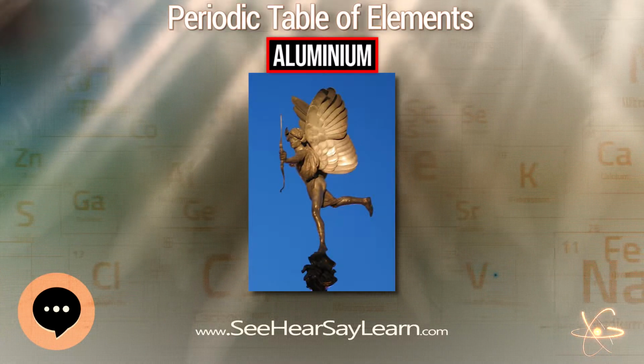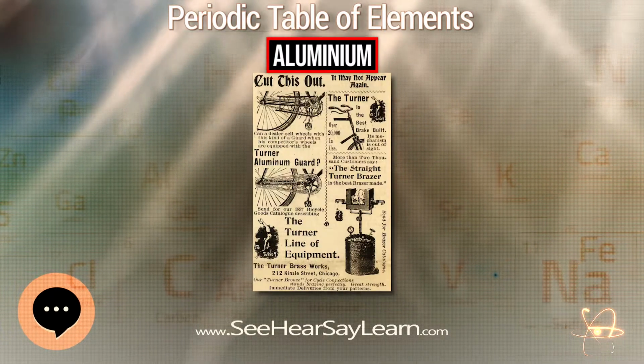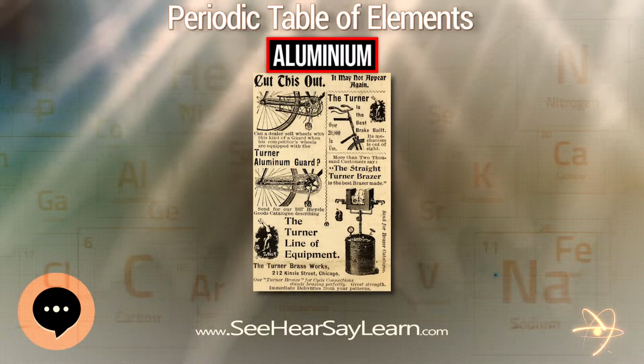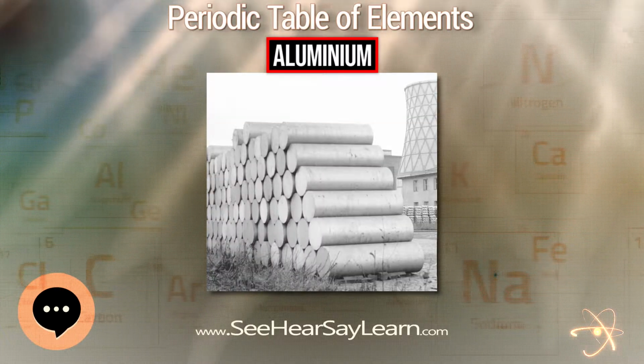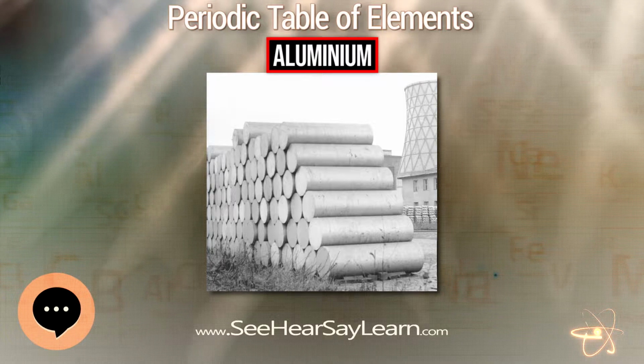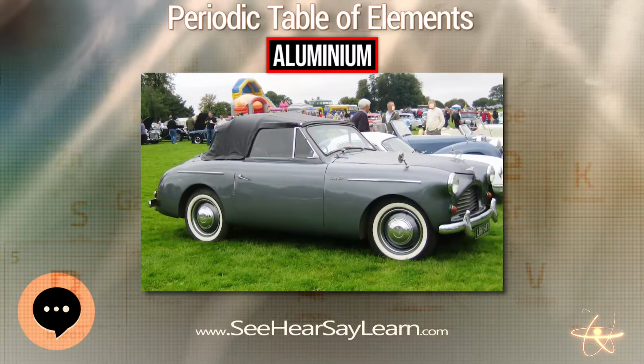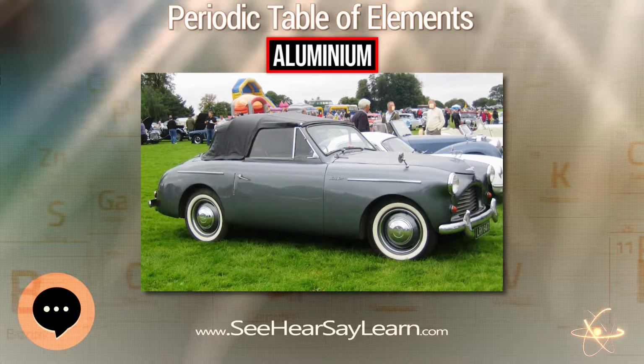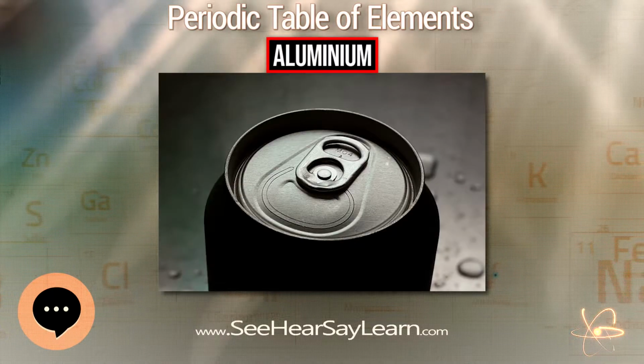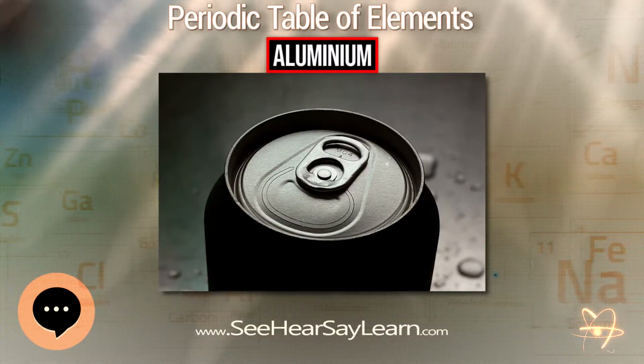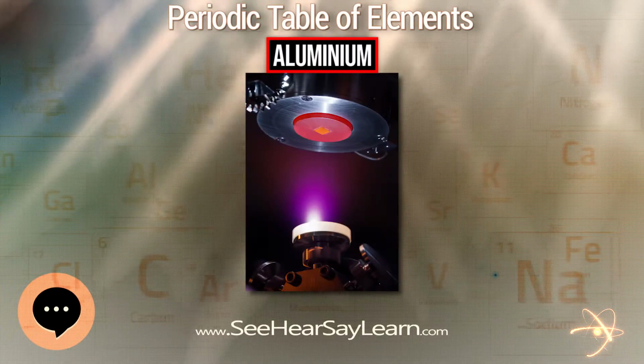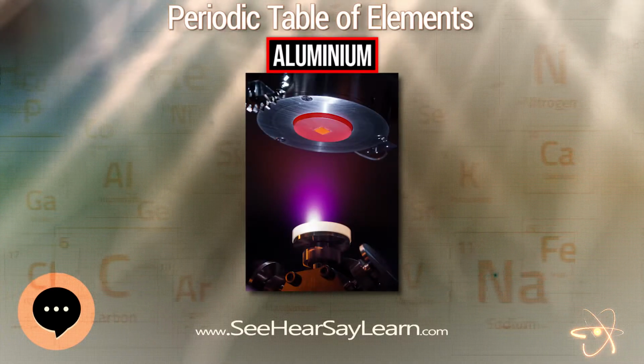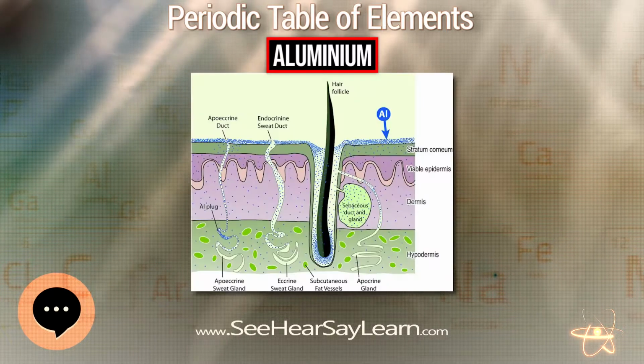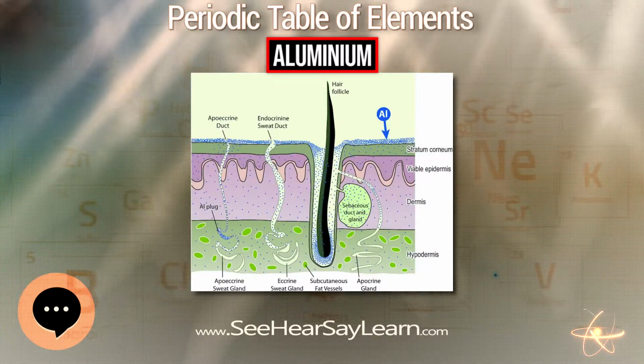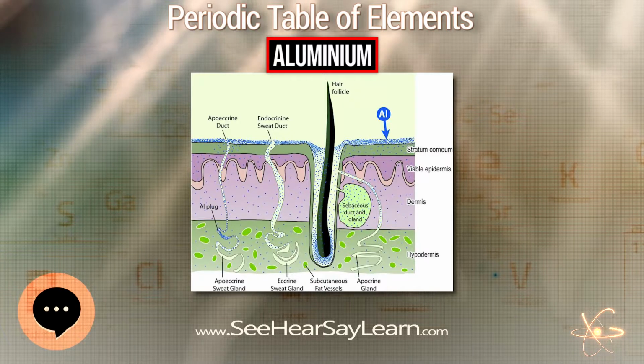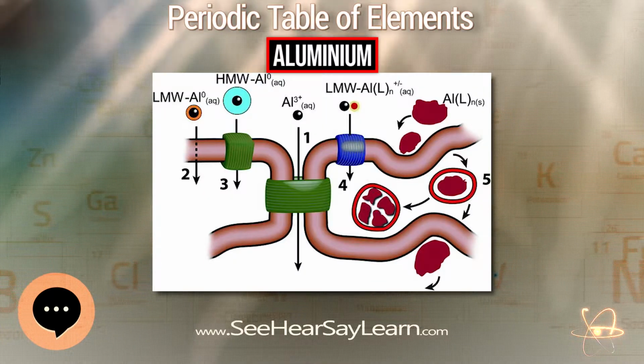The former, also called Soderberg anodes, are less power efficient and fumes released during baking are costly to collect, which is why they are being replaced by pre-baked anodes even though they save the power, energy, and labor to pre-bake the anodes. Carbon for anodes should be preferably pure so that neither aluminium nor the electrolyte is contaminated with ash. Despite carbon's resistivity against corrosion, it is still consumed at a rate of 0.4-0.5 kg per each kilogram of produced aluminium. Cathodes are made of anthracite.